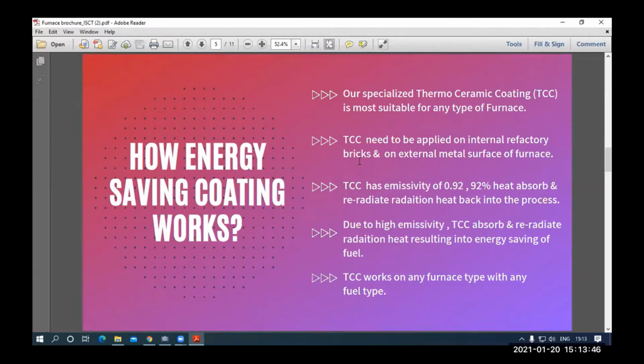Generally, the emissivity of refractory bricks or ceramic modules which are used in these furnaces or ovens is 0.4. After application of this coating, the coating thickness is around 250 microns, and with a mere thickness of 250 microns, it improves the emissivity of that particular furnace or surface. It has high emissivity. It absorbs and radiates it back in the process. So it results in energy saving to the tune of 5% to 30%.